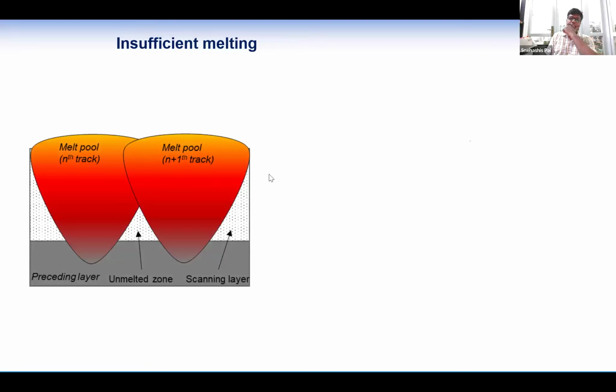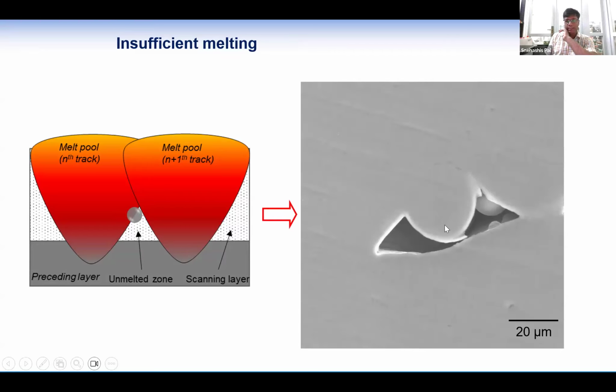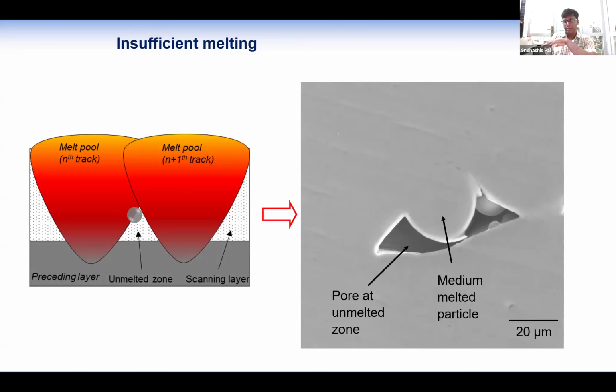Insufficient melting can occur when, let's say, between two melt pools some powder particle can get stuck there or not be well melted, and then it will look like this. There will be some portions here, and also one particle here like this. The pores are really not even. So a lot of problems can occur there during mechanical loading. Let's say this is one powder particle, and this is one melt pool, and this is another melt pool.